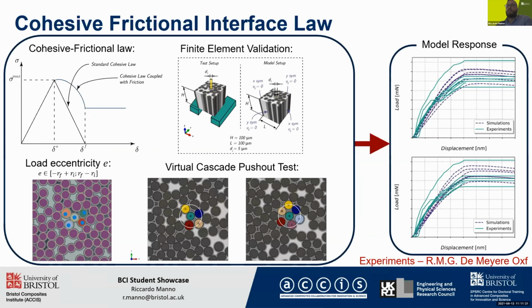We built a cohesive frictional law, which has been validated thanks to experimental work performed in Oxford, giving a quite consistent correlation. We also modeled the presence of a small value of load eccentricity and considered that this is not having any major effect on the test, as you can see on the right. So the top curve is without eccentricity, the bottom curves are with eccentricity.